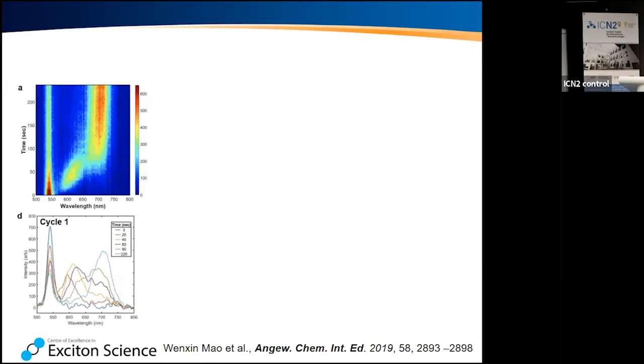Okay, and here we're plotting the fluorescence. So red means strong, blue means weak, in false colors over time. So here we see this is our bromide-rich phase that we start off with, or the mixed phase. It has a fluorescence here, and then as the iodine-rich phases are forming, you can see their fluorescence come up here at around 750 nanometers. And that happens within 50 seconds, 100 seconds of illumination. That phase segregation phenomenon comes up.